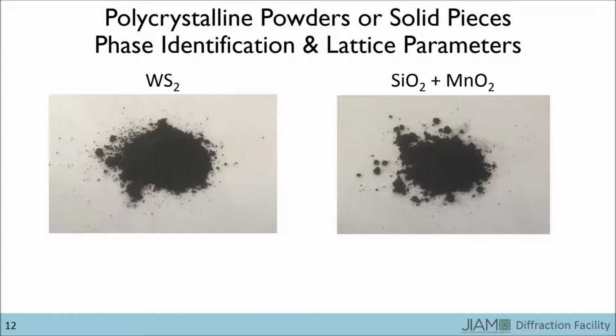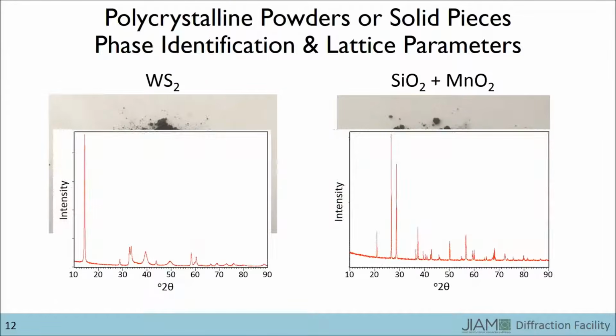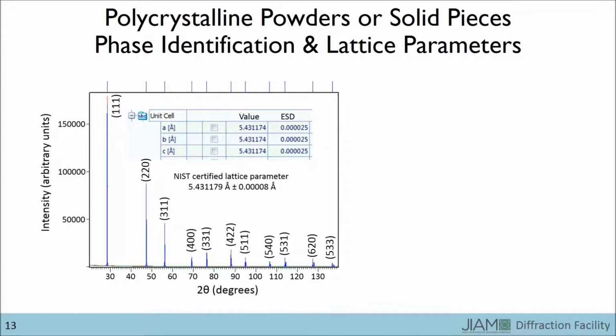Often we can't tell what a material is simply by looking at it. Fortunately, X-ray diffraction can show the differences that our eyes alone can't detect. A useful aspect of diffraction is that each material has its own diffraction pattern. The example shown here is for silicon, and each peak corresponds to a particular atomic plane as indicated. After collecting a diffraction pattern for your material, you can compare it to the PDF4 Plus database, which contains over 380,000 other patterns to find a match. Access to the PDF4 Plus database is available in the diffraction facility.